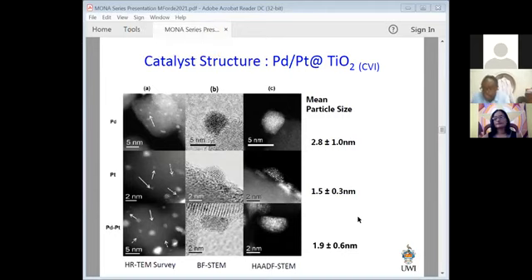So some reactions are very size sensitive, and many of the types of reactions people have been doing, for example, with CO2, hydrogenation, for example, is a good one for size, where if you have a copper particle that's 5 nanometers to 10 nanometers, it doesn't do the hydrogenation of CO2 very well. But if you have a particle that's between 10 and 20, it does it good. And if you go above 20, it doesn't. And so that's a reaction we actually have to try since we have these small particles and see if that holds for us. But in terms of the relationship, we haven't been able to pin it down because we can only make small. We haven't been able to make larger particles. The methods that make larger particles reproducibly also put other species on the surface of the catalyst. And then you have another parameter to think about.